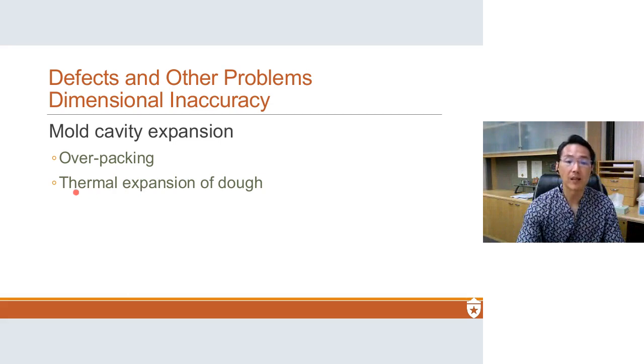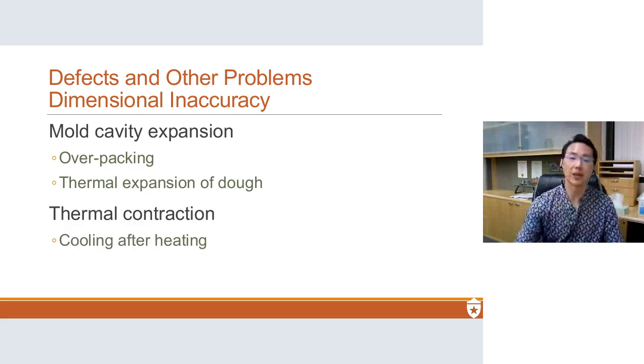But the bottom line is the system that you use has already had the mold cavity expansion calculated in. They try to match the thermal expansion of the dough, the proper packing pressure, the mold cavity expansion, and the expansion of the dough itself, so that after you're done, it actually shrinks to the correct size. Since there is a shrinkage, obviously you need it to expand so that it'll come back to the correct size. You also have thermal contraction of the mold and of the acrylic that has to be properly controlled, so how you cool after the heating is important.